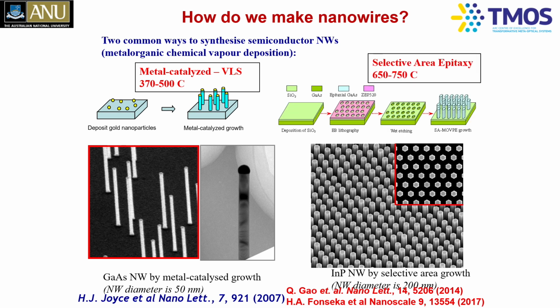And sometimes with metal nanoparticles, the use of metals is not very convenient and is not desirable. In that case, we use a technique called selective epitaxy. We deposit some silicon dioxide, put some photoresist, do electron beam lithography, create patterns of holes, and transfer those holes through the silicon dioxide, so that in these holes, indium phosphide, I'm giving an example here, is exposed.